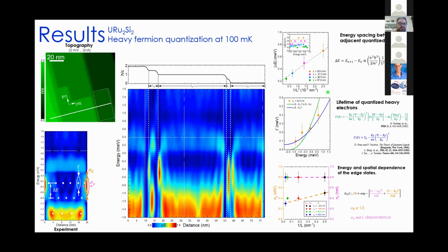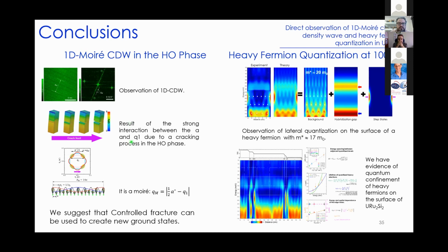So with this, I would like to conclude with these few points. We observe a one-dimensional charge density wave as a result of the strong interactions between the atomic lattice and the wave vector Q1, due to the cracking process, the cleaving process that was done in the hidden order phase. The periodicity that we found can be explained by a fractional moiré pattern between these two vectors, and we suggest that controlled fracture can be used to create new ground states. And finally, in the last part, I showed you that we have experimental evidence of a quantum confinement in a heavy fermion system, in this case on the surface of uranium-ruthenium-2 silicon-2.